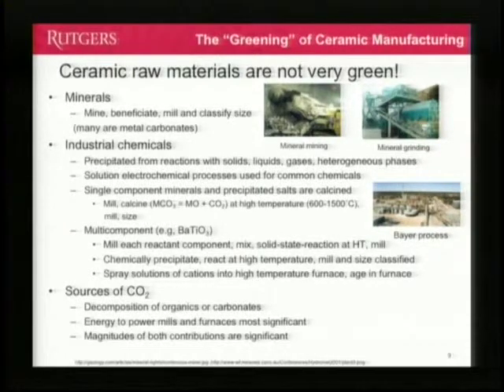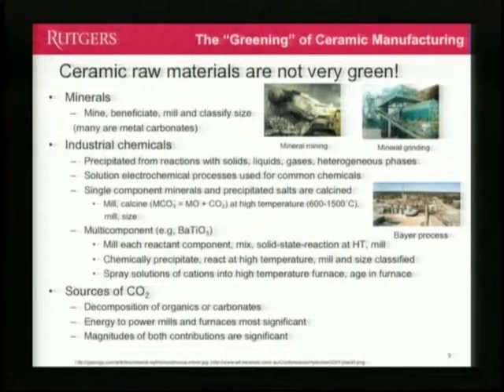So when we go look at something like barium titanate, very frequently made from a material that's either from carbonate or oxalate origin, roughly half of all of its weight loss is pretty much CO2 emissions. And then, like I said, you burn almost as much petroleum or some kind of hydrocarbon to actually make this final product. And we're only in the powder stage at that point. Then we've got to grind this stuff just like we had with the original minerals. And then after we're done grinding it, we do a high temperature reaction, as I mentioned. In this case, you may actually go through, in many cases, 2 different high temperature reactions before you're done, which would actually add another 30% more CO2 to the air. So some people get around that by spraying things into high temperature furnaces, but then you're spending a lot of energy evaporating water in addition to all the other stuff I already told you about.